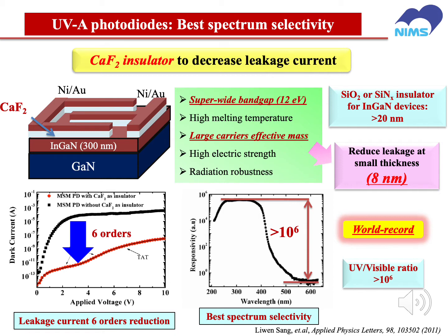And for the device, we can see that by using this calcium fluoride, the leakage current is reduced by more than 6 orders of magnitude. And also the device shows a very good spectral selectivity. The ratio between the UV light to the visible light is more than 10 to the 6, which is also the highest value ever reported, also compared to other UVA photodiodes.